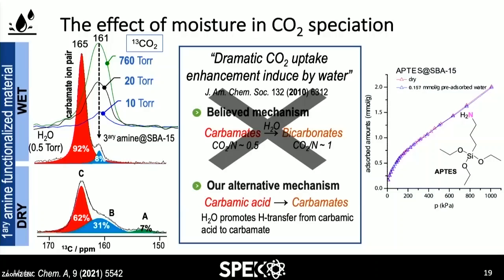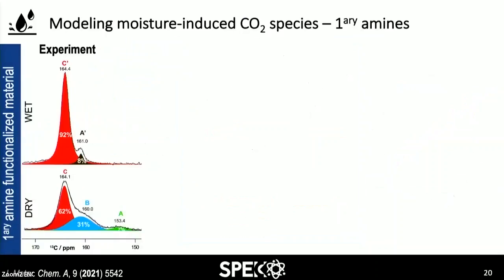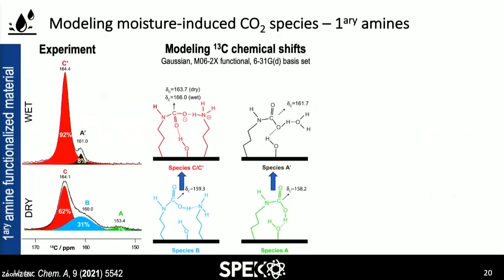The alternative mechanism that we propose is that the carbamic acid converts into carbamate because water promotes a proton transfer from the carbamic acid to the carbamate. And obviously we have performed modeling on the structures to be able to confirm our hypothesis. And as you can see, when species A becomes in contact with water, it forms hydrogen bonded carbamic acid species, which is this one here that we call A prime, and species B converts to species C.